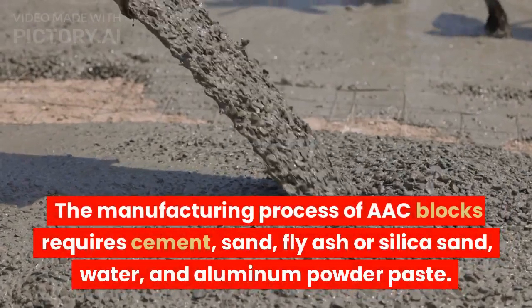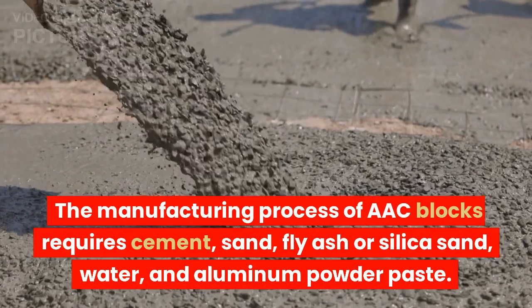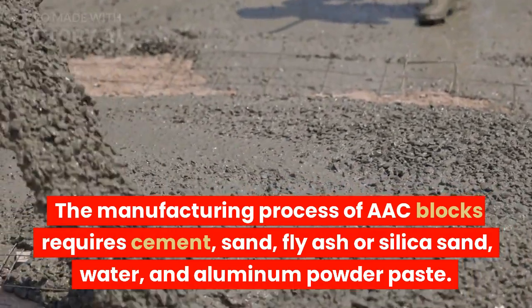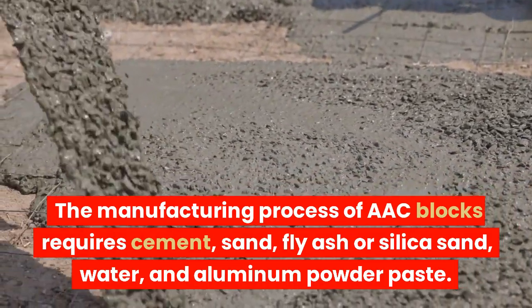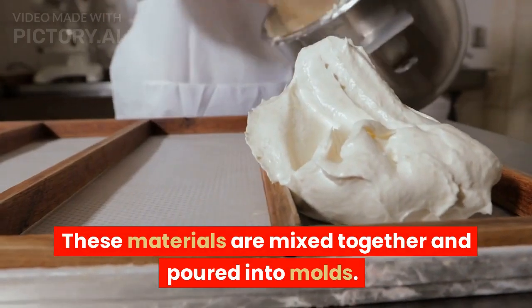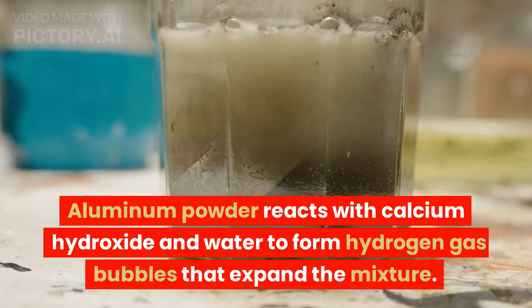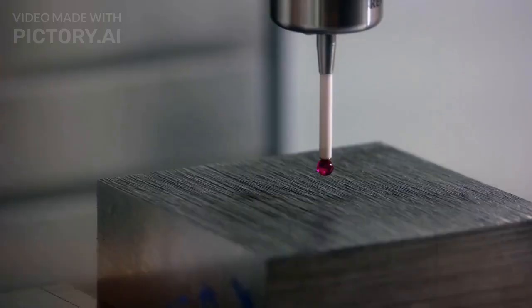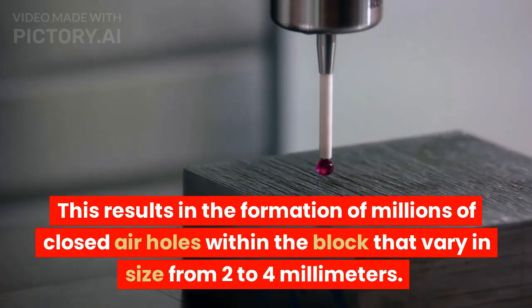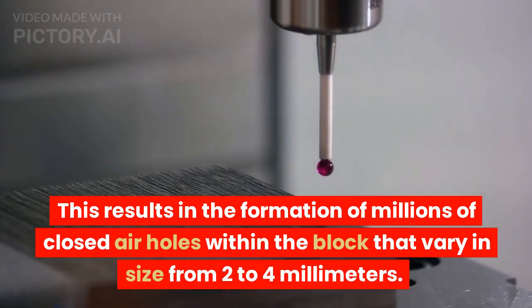The manufacturing process of AAC blocks requires cement, sand, fly ash or silica sand, water, and aluminum powder paste. These materials are mixed together and poured into molds. Aluminum powder reacts with calcium hydroxide and water to form hydrogen gas bubbles that expand the mixture. This results in the formation of millions of closed air holes within the block that vary in size from 2 to 4 millimeters.